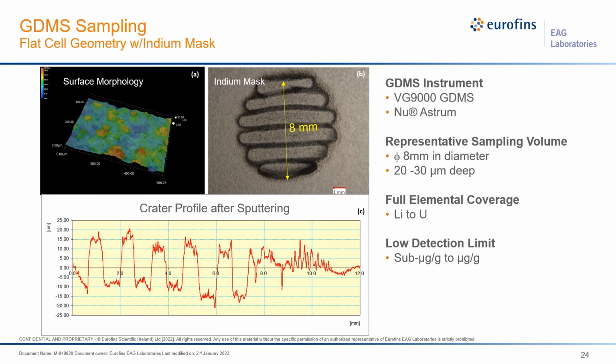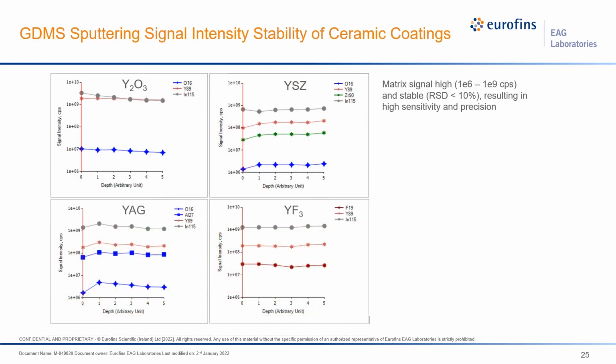Okay. So the first thing for any method development or validation is you look at the matrix signal. Can we actually spot it, successfully spot it? Number one. Number two, if it does spot it, what's the signal stability? Number three is how strong the signals are, because those will establish what the precision looks like, or what your sensitivity looks like, or what your reporting limits will look like.